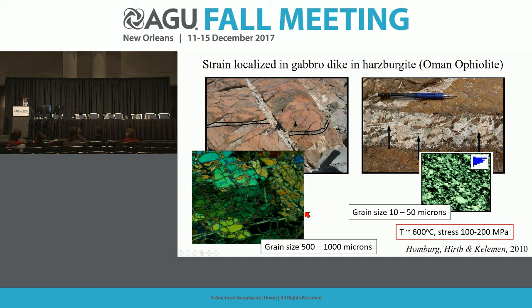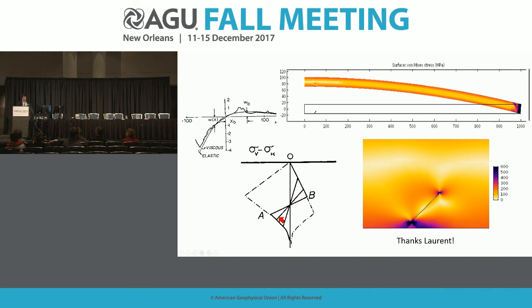So putting that together with the data that we were just looking at, I began to wonder if you can envision a scenario where you have a weak dike that upon bending, that weak dike or pyroxenite or whatever it is can deform, and you end up with large stress concentrations that allow the nucleation of earthquakes in the brittle peridotite around it.